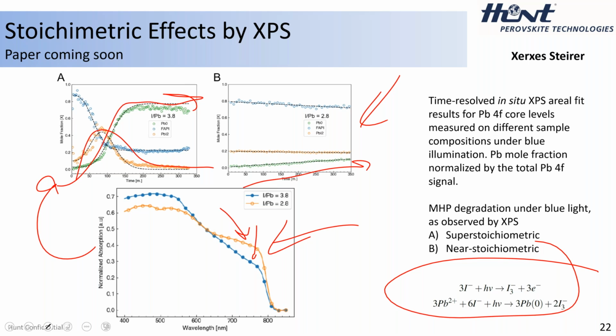And so absolutely yes. We're taking an Arrhenius type approach, looking at the different thermally or light activated degradation mechanisms, calculating their energies of activation, and then estimating actual device lifetime based on the application of the Arrhenius equation. So we're digging down into that. We want to get real numbers and understand exactly how long the device would last, far beyond IEC testing.